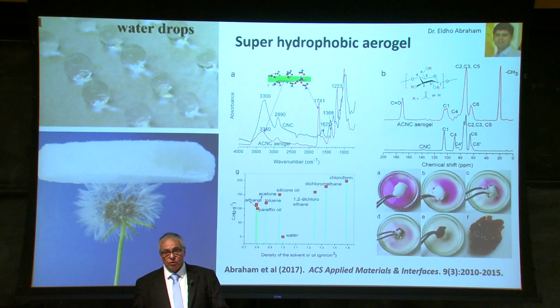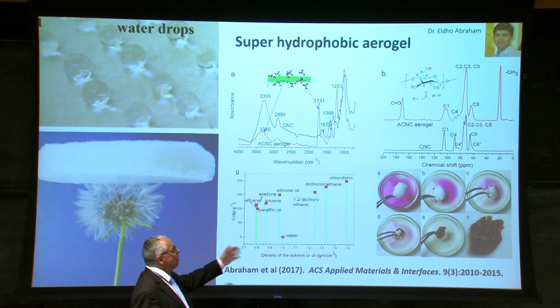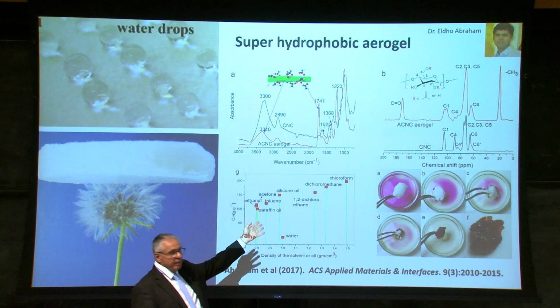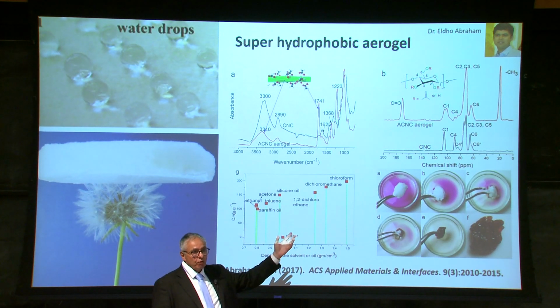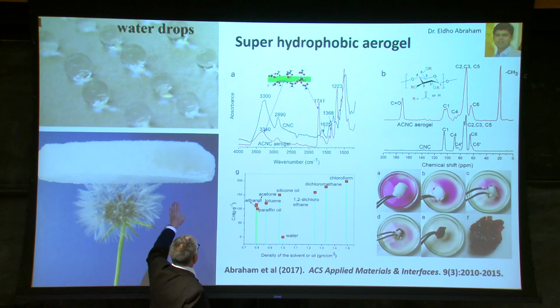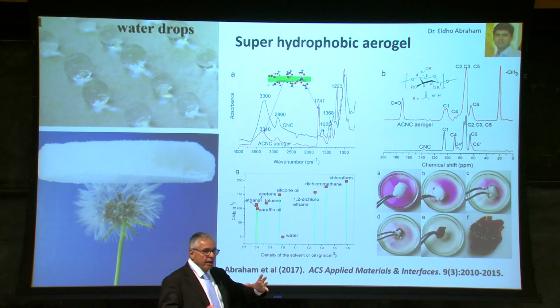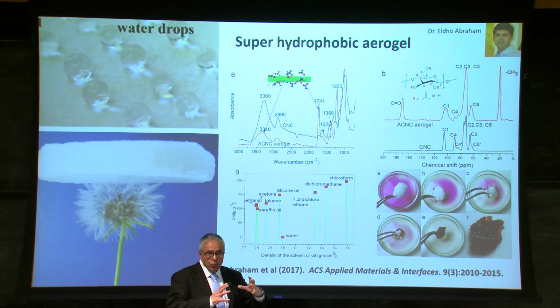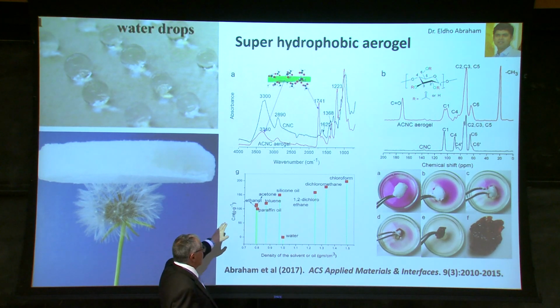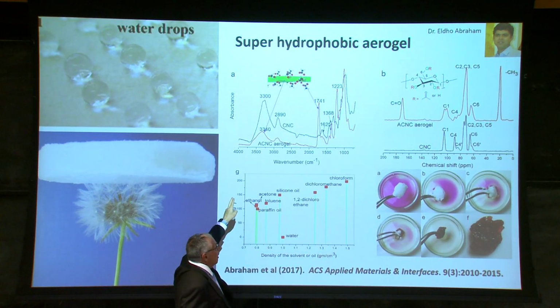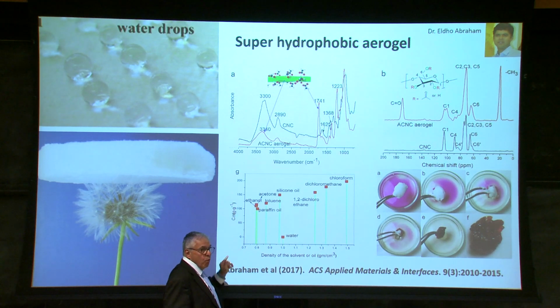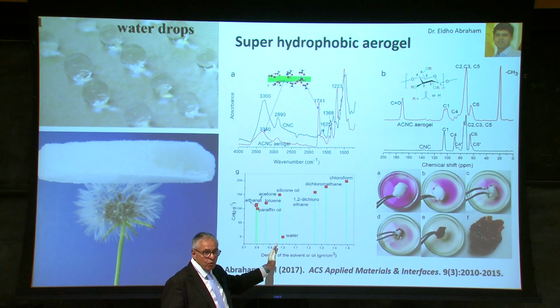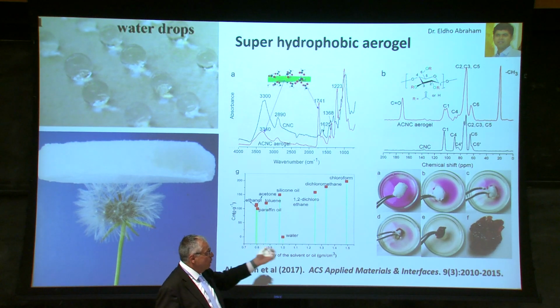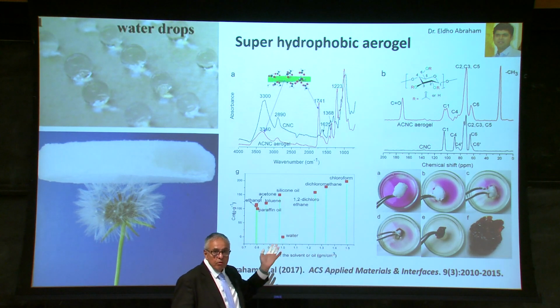But sometimes you would like the material to be hydrophobic. And so we've developed some chemistry, very easy chemistry, to acetylate cellulose nanocrystals, make them super hydrophobic. And we've been able to make aerofoams. From here you can see very light. One interesting, and also we can see it's super hydrophobic. But the beauty of that foam is that it has an absorbent capacity for a wide range of organic solvents. Like, for example, here we can absorb 200 times the weight chloroform for 1 gram of the CNC foam. So you can imagine that we can remove oil spills from the ocean or lots of other things.